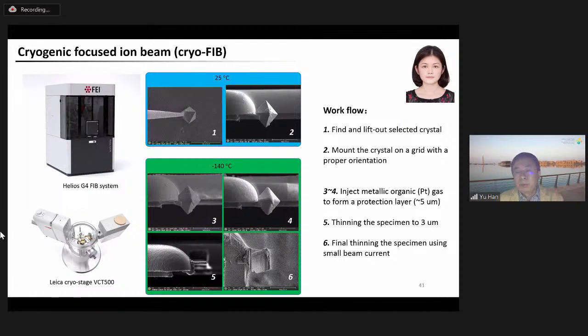Well, FIB is normally performed at room temperature and is commonly used to cut hard materials, right? And is considered unsuitable for soft or unstable materials, okay? Because the ion beam can easily damage their structure, right? If the materials are unstable. Okay, well, we found if we perform FIB at cryogenic temperature, say liquid nitrogen temperature, this low temperature can effectively reduce the structure damage effect. So here we use a MOF material called HKUST-1. This is a millimeter-sized MOF crystal, as an example to show you how a cryo-FIB works.